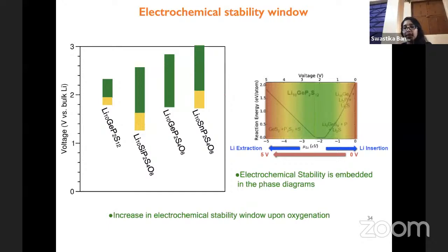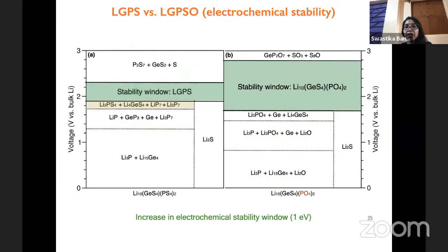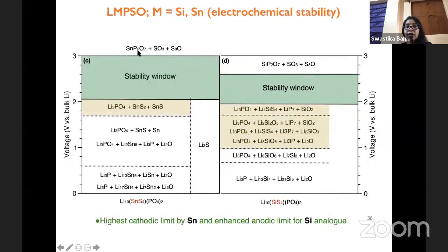So this is a superior compound or superior design for the next solid electrolytes with respect to the state-of-the-art LGPS. So if we see the stability window, you can see the products which form below or above the oxidation or reduction limit, and you see the stability window is actually much more enhanced, and you can basically tune it through such a strategy. And if you change from silicon to germanium or tin, or sorry, germanium to silicon or tin, you can again have the freedom to push the oxidation limit higher or the reduction limit lower, or to tune that. So this is a smart approach, again, through designing the material to make them more applicable depending on